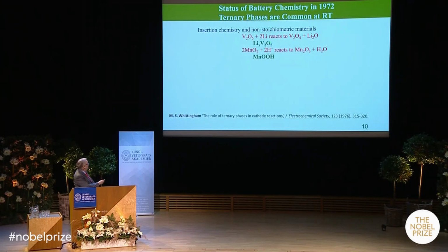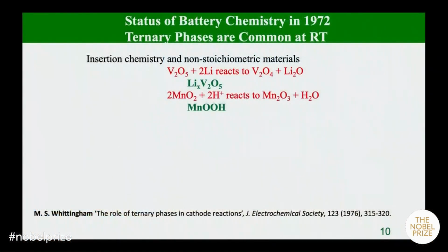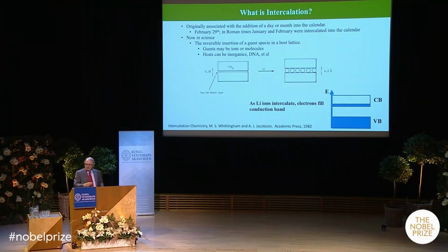So what in fact happens in these cases, you get lithium ions inserting into this one, and you get protons going into the manganese oxide, forming manganese oxyhydroxide. And this really led to the whole concept of intercalation chemistry within battery materials. And we just published this in 1976. So let me briefly describe what intercalation is. If you get an old dictionary, let's say from the 70s or 80s, this is what it will say.